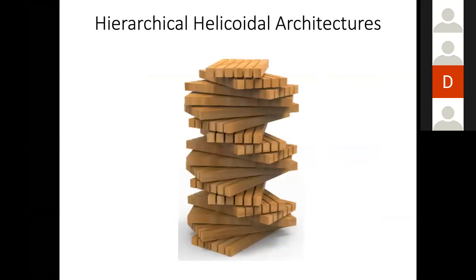Okay. The other architecture that we are mainly interested in is the helicoidal one. What does it mean? If you have done a little bit of material science in your previous years, a good way to build material in nature is to use fiber reinforcement. If you have these fibers, you can change the direction in which you build up your fiber composite, and you can improve the mechanical properties. What is interesting is that if you use fibers that are birefringent, like in the case of cellulose, you can exploit an architecture like this helicoidal one, which is really good for mechanical strength and also for optical properties. The only requirement is that the periodicity between layers that have the same orientation is comparable with the wavelength of light.